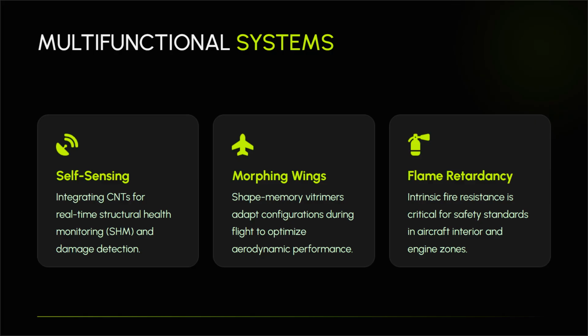Furthermore, Vitrimers open the door to advanced, multifunctional aerospace composites that go beyond simple structural support. For instance, by integrating conductive nanofillers like carbon nanotubes into the Vitrimer matrix, we can achieve structural health monitoring. This allows for real-time sensing of internal damage via electrical resistance changes, and it can also enable joule heating to trigger localized self-healing or de-icing.